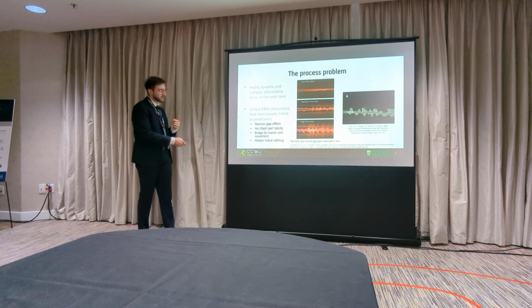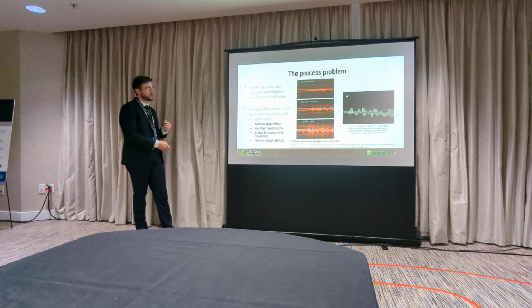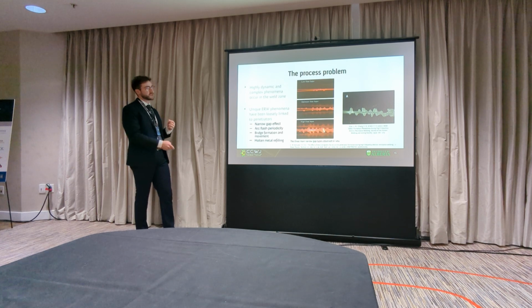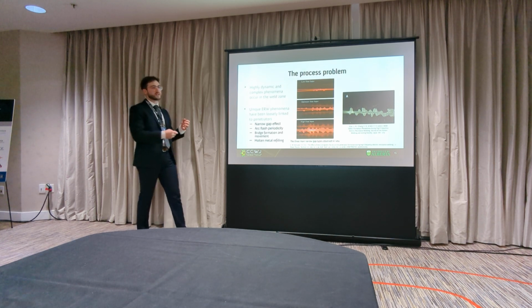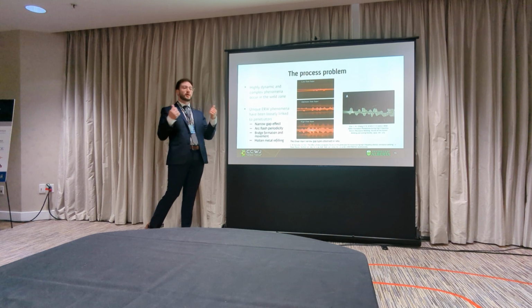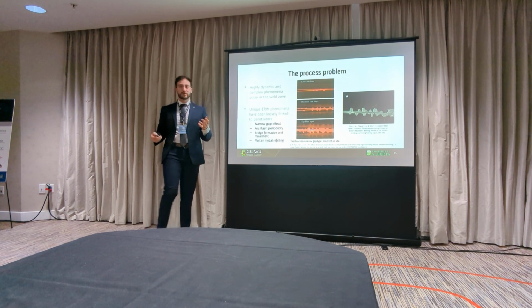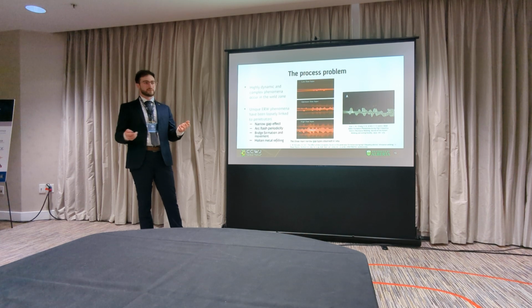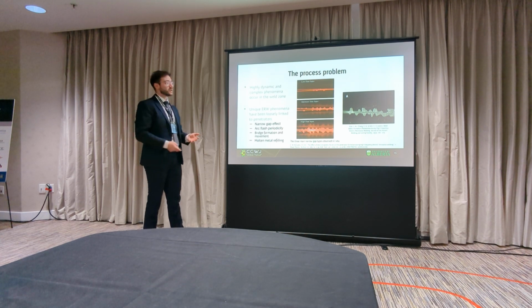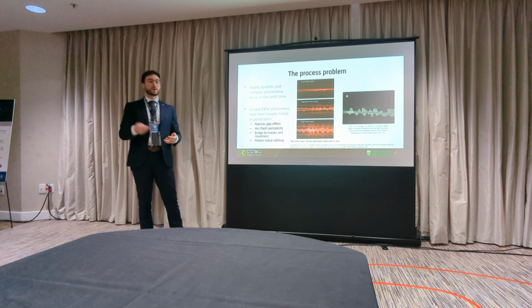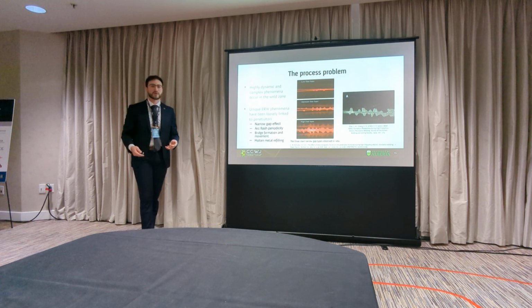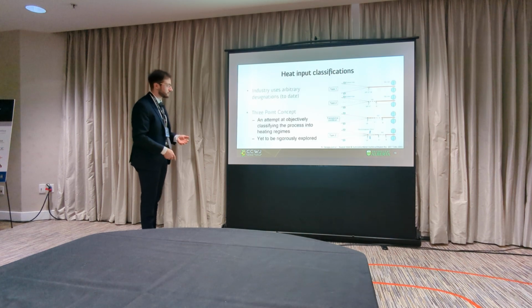And these 3 effects can lead to molten metal refilling. So this is a top-down schematic of the V, and this red metal here is metal that has been expulsed out of the V. So it's out of the V, and when we have hot metal that's molten outside of the closed interface in an oxygen system, you can get oxides. So when this metal is thought to re-enter the V, that's when we get oxides in the weld zone, and those are the penetrators that we're talking about.